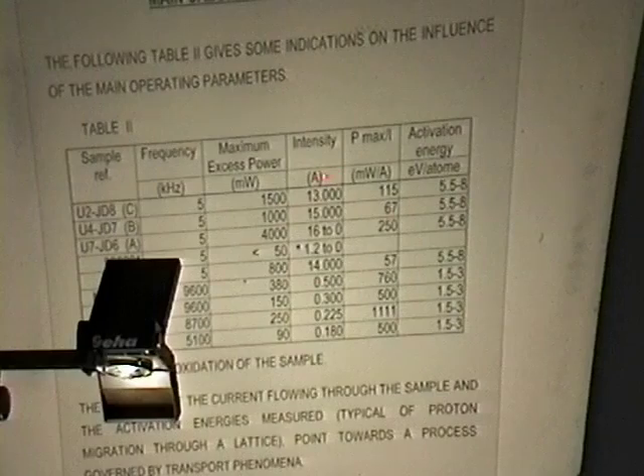And one thing interesting you can note, this is the intensity. You can see that the 5 kilohertz experiments have a lower milliwatt per ampere than the megahertz experiments, which are higher. And the activation energy is higher for the medium range frequency and lower for the high range frequency. We have no clear explanation for that, but we think it's related to the synthesis of this Hydrex compound that we are going to talk about.